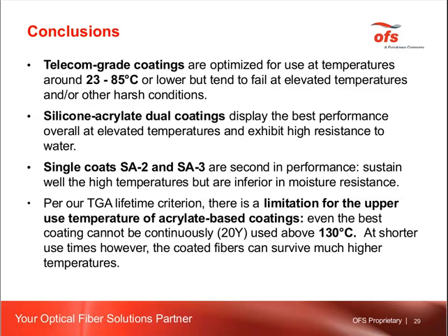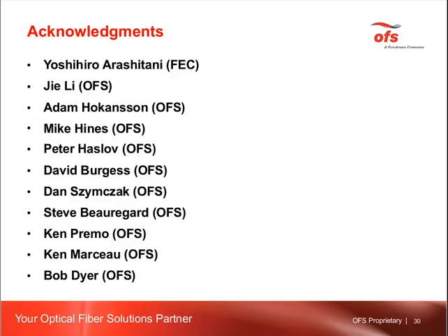Once again, 85 degrees C is the rating for telecom grade coatings. If we believe in this rating, then we should believe that the highest upper use temperature for acrylate-based chemistries is probably about 130 degrees C. If we want something with higher temperatures, then we probably should use a different chemistry, like, for instance, polyimides.